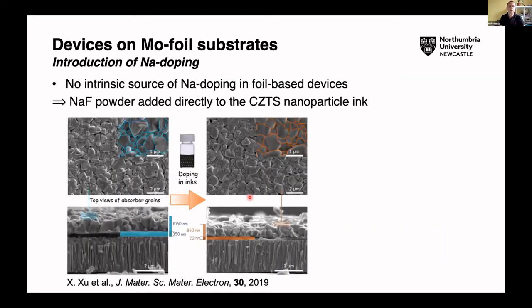One of the issues with these substrates I mentioned, like the foil, is that they don't have an intrinsic source of sodium doping. So this was a technique we came up with to introduce doping directly into our nanoparticle ink. So these are the dopants schematically included in the ink here. So we dissolved sodium fluoride powder directly in the ink. And when you do that, you get a nicer absorber in top view, and it is slightly thinner.